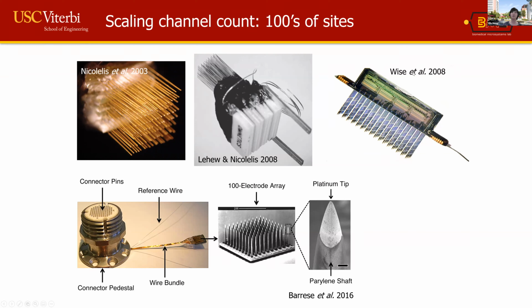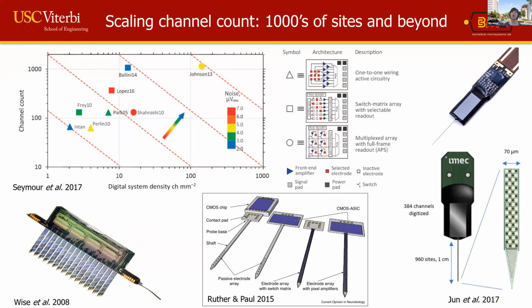And this is very easy to do in the Michigan approach, where you can integrate electronics on the back end of a probe. And they've explored one modality, and there are many other groups that have actually done this as well, using slightly different approaches. And in general, the message is that you could start to think about devices that are at thousands of sites or beyond. And there are devices available commercially now that will allow you to get close to about 1,000 sites. Right? So this is all positive progress.